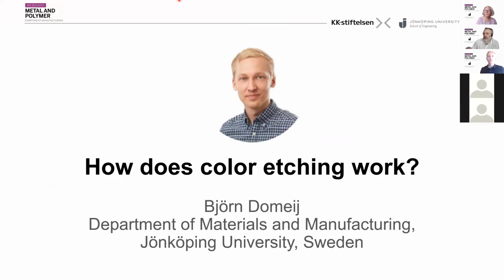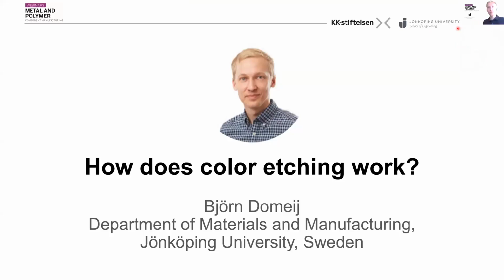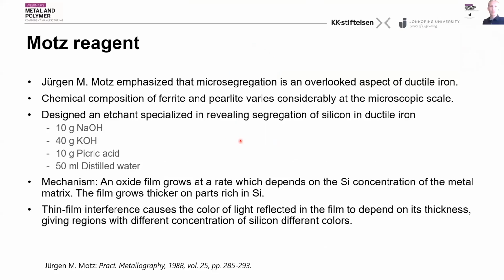So I will focus on how the color etching works, and also a bit about how you can interpret these colorful patterns that emerge when you do the etching. There is more than one way to color etch, but the one we feel is most important, and that we have most experience with, is based on an etchant developed by a gentleman called Motz. He emphasized that microsegregation is often an overlooked aspect of ductile irons. And he noted that the chemical composition of both ferrite and pearlite actually varies considerably at the microscopic scale.